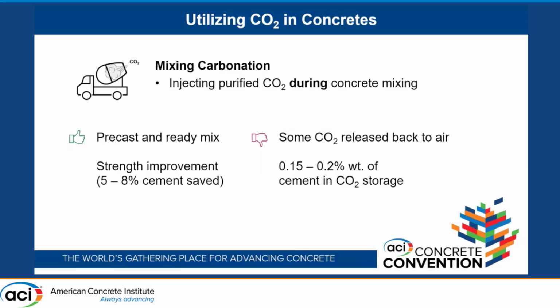So a step further into this would be the alternative of mixing carbonation, in which instead of waiting for you to cast the member and then cure under CO2, you would inject the CO2 directly into the truck or the mixer, so that reactivity could happen during that process. And so now you have more applicability. Now you're open to either precast or ready mix and bigger members. And you do see strength improvement as well, even though it's still not that expressive.